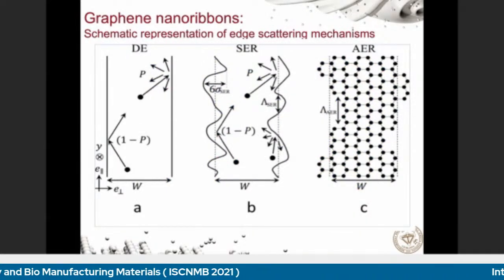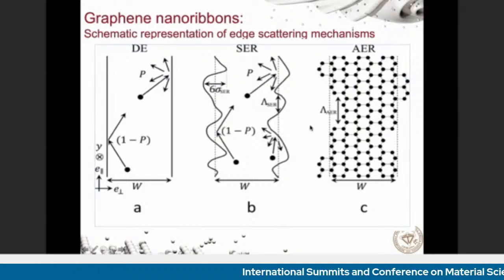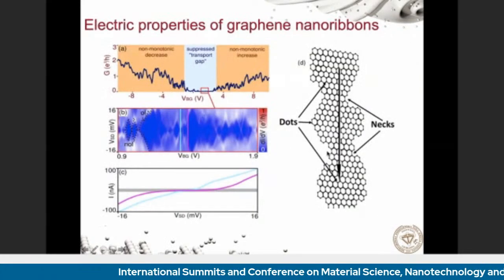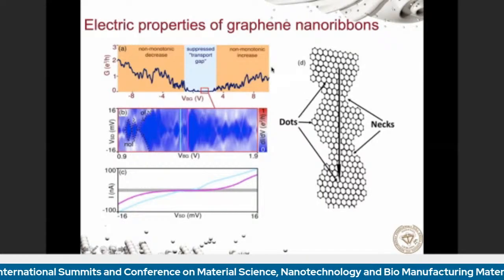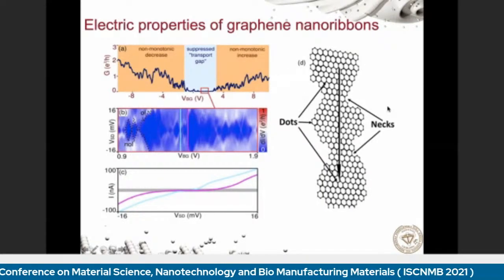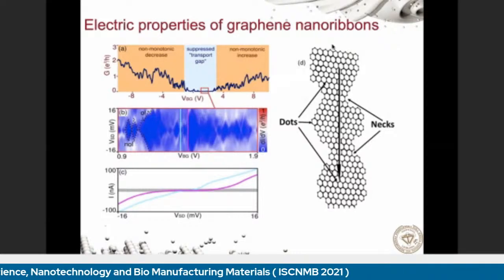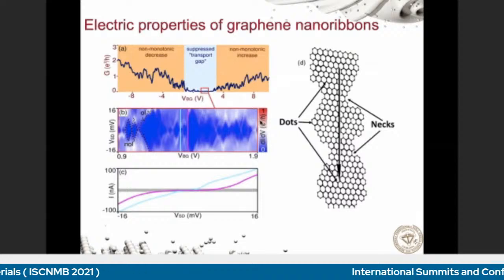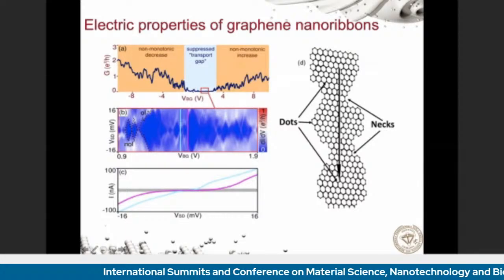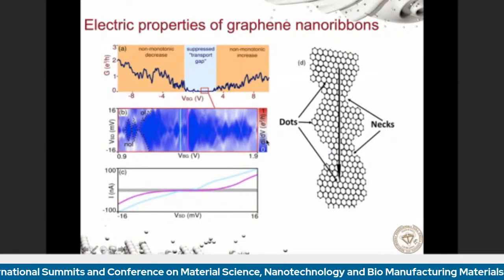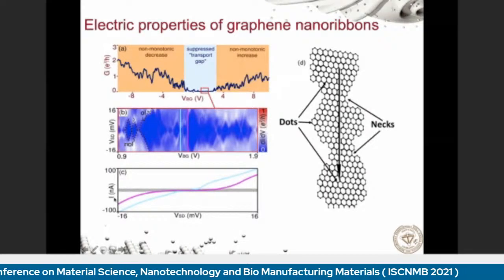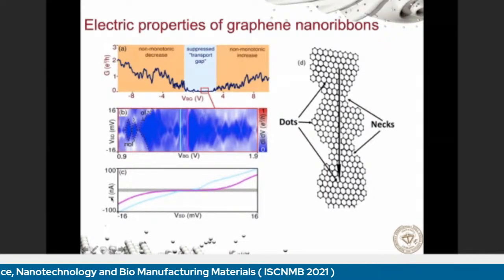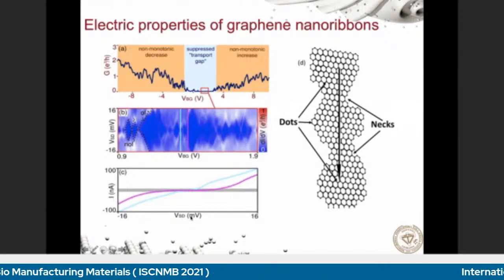So if you look at the graphene nanoribbons, for example, here you have the structures and what happens with this edge scattering mechanism. Another interesting property are these electric properties, which means that if you shape these graphene nanoribbons, you can get, for example, a suppressed transport gap here on the left-hand image, which is, of course, very useful for electronic properties. So that means you shape the dots and the necks in such a way that you can get a suppressed transport gap. And you can see here the characteristic current as a function of voltage.